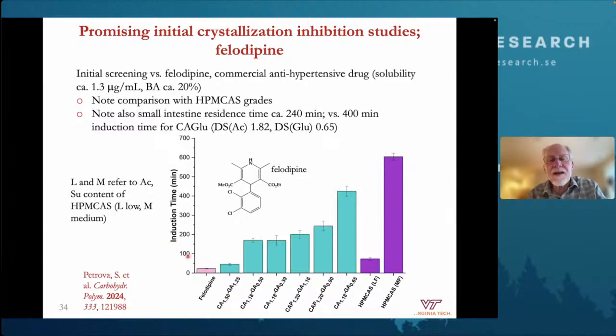And what you can see is that we see differences in the time that it takes for the felodipine to start to crystallize. For the better polymers, that time is on the order of 400 minutes, well over 6 hours. The time a drug takes to get through the absorptive part of your GI tract is about 240 minutes. So this is preventing the drug from crystallizing for a longer period than it could possibly be in the absorptive zone of your GI tract. And it's better than one particular grade of HPMCAS, not quite as good as the other.